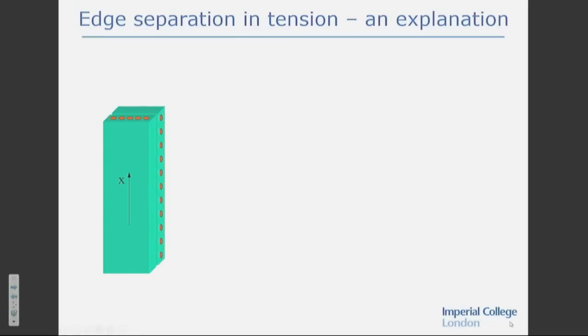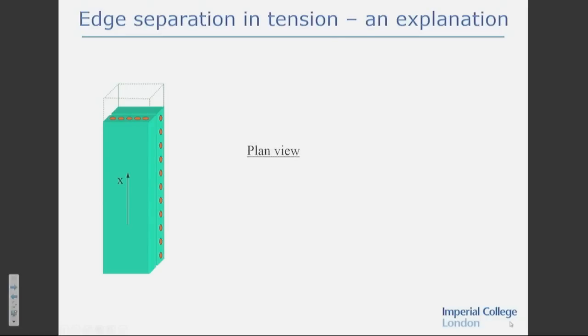So there it is. Now imagine in the test, we put an extension in the vertical direction like this. And I'm going to look at the plan view of the specimen, but before we go there, think about this. This front ply, with the fibers going vertically, when you extend it longitudinally, it wants to contract laterally. The rear one, with the stiff fibers running horizontally, contracts laterally as well, but very, very little. So the front one wants to contract a lot laterally, the rear one doesn't want to contract at all, and yet, of course, they're not free to just do that because they're bonded together.